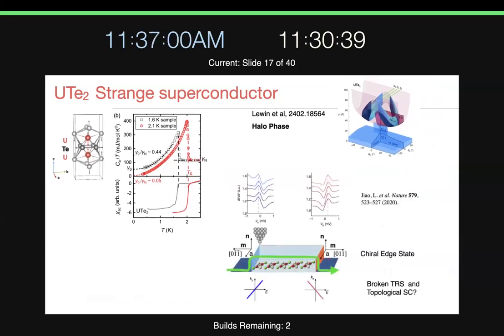So in this particular system, there are some indications of broken time reversal symmetry. One of the indications is that if you look at STM measurements of this system, you can find indirect evidence for the presence of a chiral edge state. This chiral edge state is seen through the Doppler shift in dI/dV, and the authors of this particular paper interpreted this in terms of a linear combination of two different representations of pairing: pairing 1 plus i times pairing 2, which then produces a topological state.